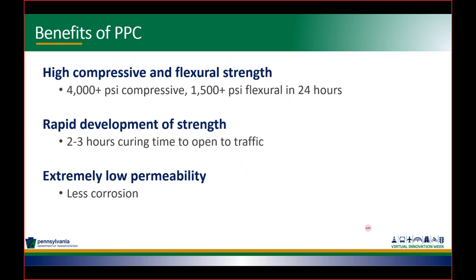So a little bit about the benefits of polyester polymer concrete. PPC has a very high compressive strength and flexural strength, and it can develop strength very rapidly. So in 2 to 3 hours, you can open to traffic and overlay. It also has a very low permeability, so it protects the deck and the substructure under.